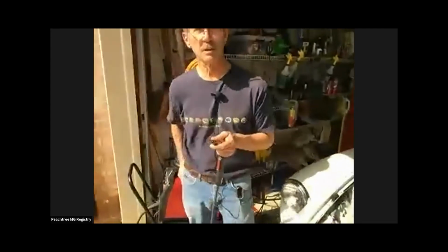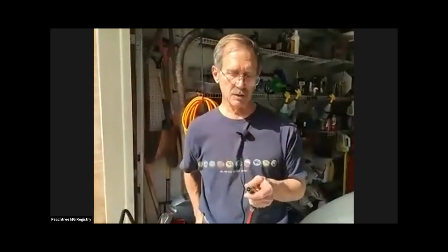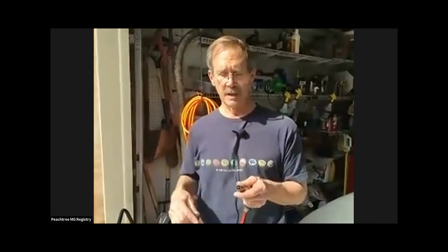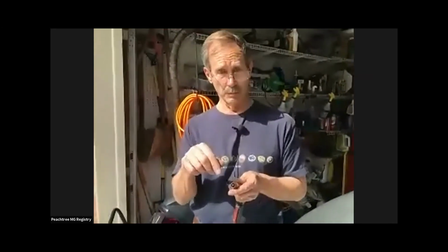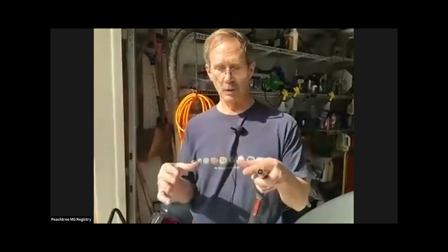I think I read that the mild carbon steel that we're welding melts at 2,700 degrees Fahrenheit. An arc in a MIG welder starts at about 5,700 and goes up. So it's an instant melt. So the electrode melts, the arc melts the metal surrounding it. Therefore, this way we can weld those pieces together. And the wire also acts as a filler. It's an automatic filler that you're doing.